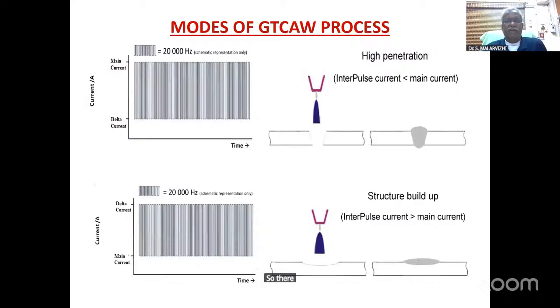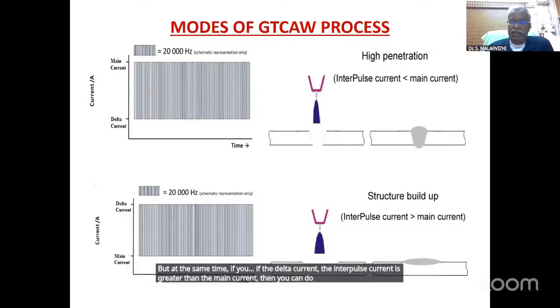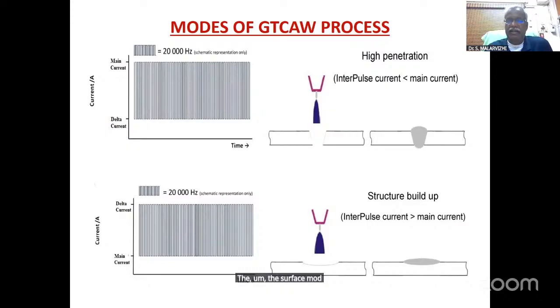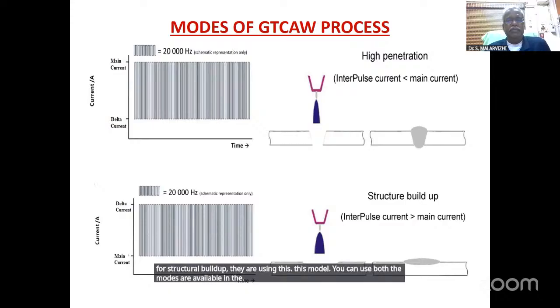There are different modes available in this process. If you want to weld, then you have to go for the high penetration mode. In this, the interpulse current, which is the superimposed delta current, is lower than the main current. If you use this condition, you will get deeper penetration. But if the delta current, the interpulse current, is greater than the main current, then you can do surface modification like cladding and hard facing. Also, you can do structure buildup. They use this mode. Both modes are available in the process.